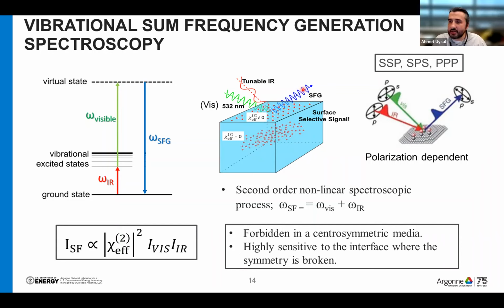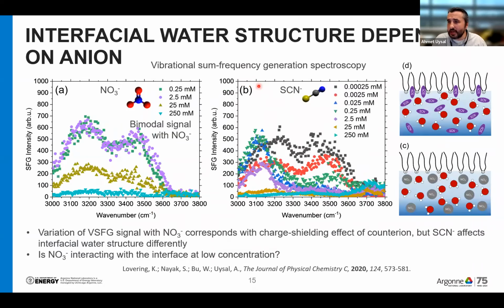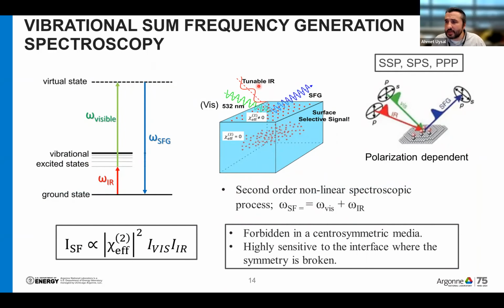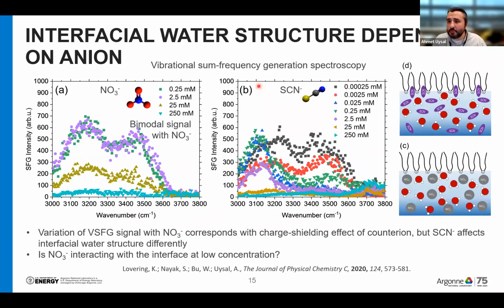Depending on the structuring at the interface, we are getting very nice information about the interfacial structures. And since we can tune this IR, we can go to different vibrational modes, and we can learn about the structures at the interface. For example, in this case, we are looking at the OH band of water at the interface. So we are trying to understand indirectly how these ions are adsorbing at the interface and changing the water signal. This bimodal signal that you see is very typical at the air-water interface. When you have a surfactant, the charge of the surfactant orients your water molecules, and it gives you a very nice signal at the air-water interface.